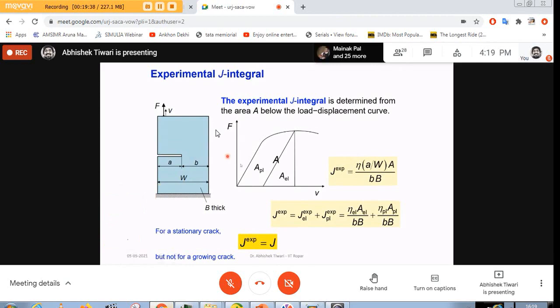We take the area under this curve, which is related to the energy consumed. You can change force to stress and displacement to strain, and then you get strain energy density. Here we are taking the area under the force-displacement curve, so we need a factor eta, and then divide by the cross section of the part of the material which is taking the load, and then you get the J integral experimentally. But the problem is that we are also counting the plastic part here.